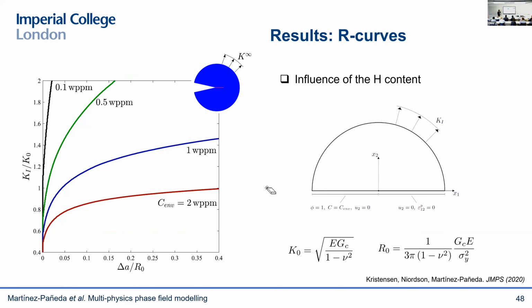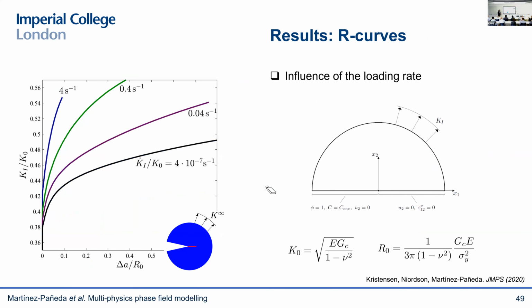So some representative results, these are R curves, crack growth resistance curves. So this is a measure of the crack tip stress, the applied load. This is the crack extension. And you can see, as you would expect from the experiments, that as you increase the hydrogen content, you lower your fracture resistance. This is another well-known experimental observation, sensitivity to the loading rate. So if you load your sample very slowly, then you let enough time for the hydrogen to accumulate in the fracture region, and therefore you lower your fracture resistance.